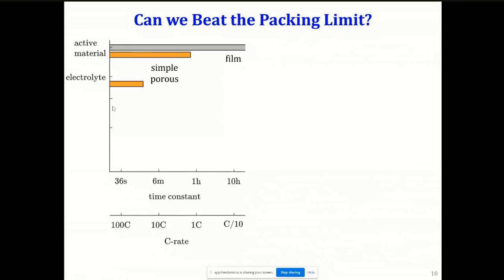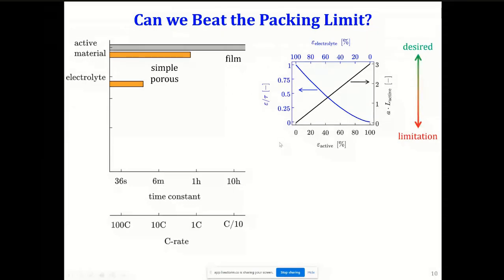Now, one of the ways we try to increase the energy density of these batteries is increasing the packing. And what we are looking at is we want to put more and more active material, because that's the phase that actually stores energy, and you want to reduce everything else. And if you do a back of the envelope calculation, you get these lines where your active area increases with more and more amount of active material you put in. Now, if you're putting in active material, you are simultaneously decreasing the amount of pores that is available. So you're simultaneously decreasing the volume of electrolyte. That's why the top axis goes in the opposite direction. And at any point, both of them sum up to 100%.